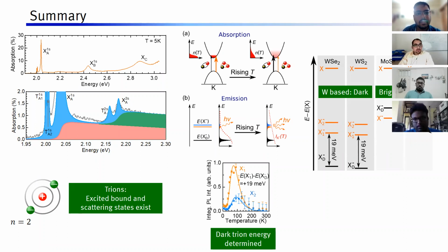Yeah, so this is what we are doing actually. So you have these two trions which appear below this exciton state. So the energy difference between this exciton and this trion state will exactly be that electron-electron correlation interaction energy. Yeah, so this is the binding energy of trion. True, true. Yeah. And as you increase the temperatures, the PL peaks of the excitons also shift to the left in energy. So why is that?